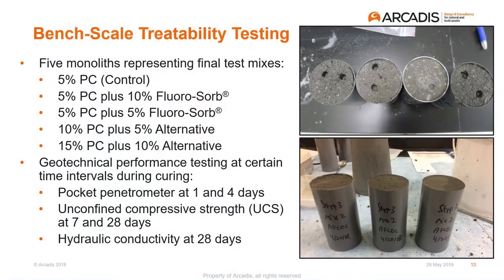So we needed to have some degree of unconfined compressive strength returned to existing conditions, and we really couldn't allow for the soil to self-settle over time, even though this really was in the back 40. So we added a variety of concentrations of Portland cement. I'll explain why 10 and 15 were used with some of the alternative products, but Portland cement in the quantity of 5% became our control. So whereas Shadi had unamended controls, I used Portland cement only as the control, because the base case was that we needed to mix the pit up and at least regain some unconfined compressive strength.